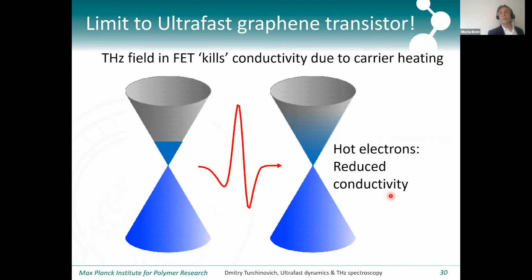So it means that the device is not hot in the sense that you're not heating up the phonon subsystem substantially. This reduced conductivity really is due to a separation of timescales between the ability to heat the electronic heat bath in graphene with a short pulse and the relatively slow electron-phonon coupling, which then thermalizes the whole system and effectively brings it back to this state here. So within a few picoseconds after you have this hot state, it cools down. But you will reach a steady state in a device where you keep heating up the electrons, and they will have a reduced conductivity.